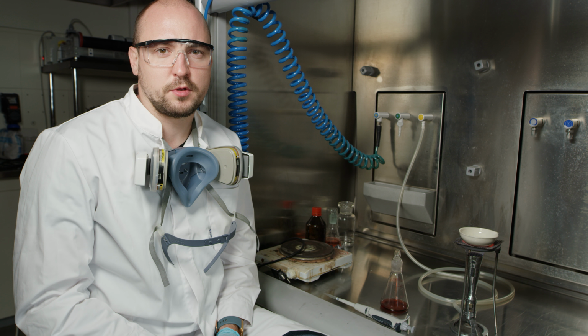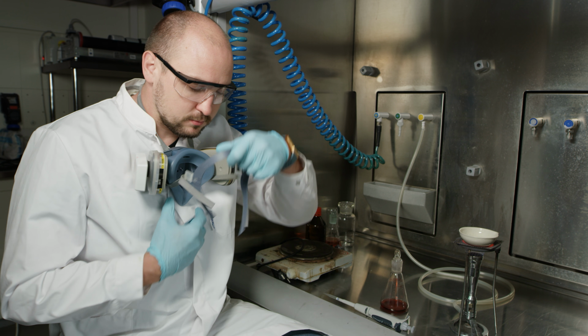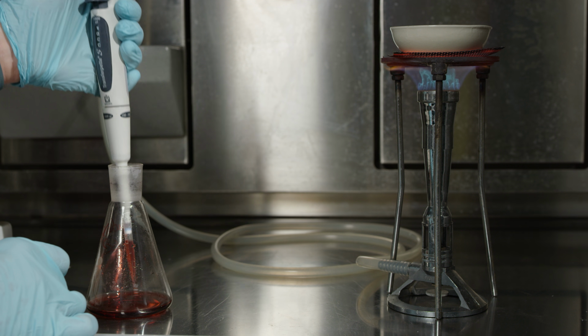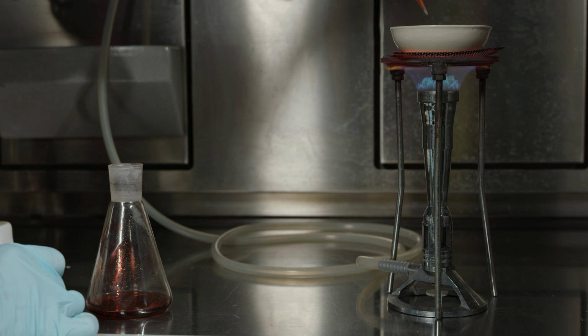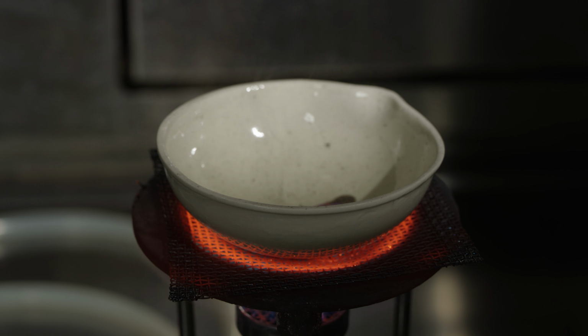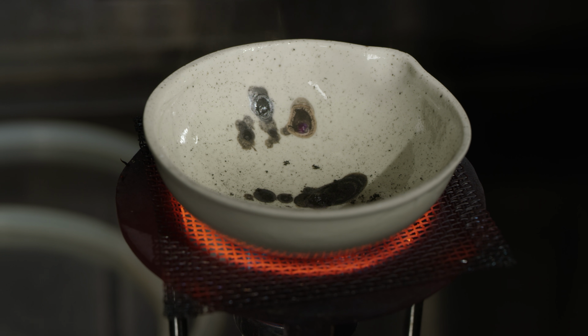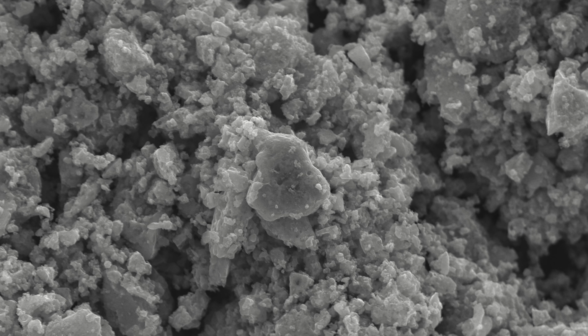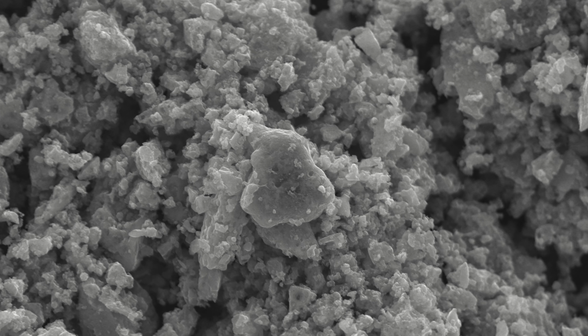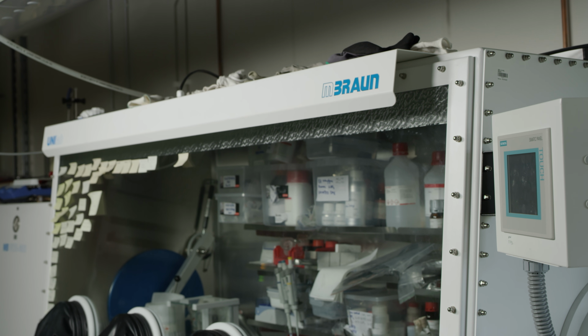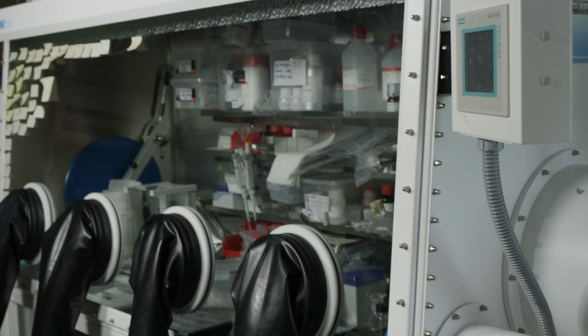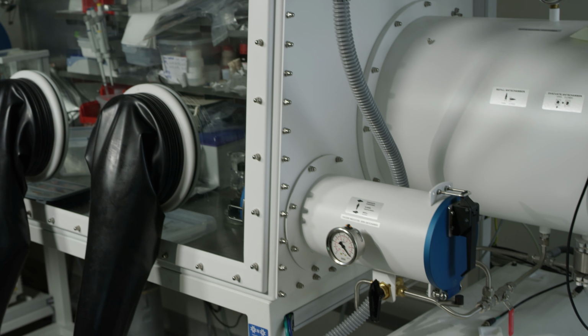Cathode material is produced using glycine nitrate process in which all the vanadium salts are first dissolved and then the mixture is dropped into a hot crucible, which will lead to a violent combustion reaction to form fine particles. In the SEM image you can see that it's made of particles with a varying size distribution. Everything is handled in a glove box to avoid contact with moisture and air.